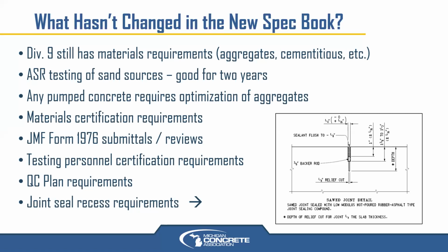Your materials cert requirements are still all that they've been, as far as if you're a pre-qualified aggregate supplier, and the reduced testing from that, versus, what's 1 per 10,000 tons, except on optimized jobs, which is 1 per 5,000 tons. If you're not a pre-qualified ag supplier, you got to do a test every 1,000 tons, et cetera, et cetera. So that's still the same.